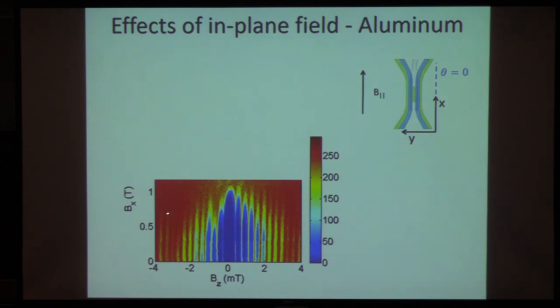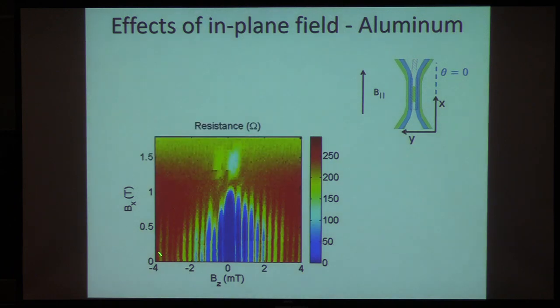And first we thought, oh, this could just be we're killing superconductivity in our leads. This is aluminum, we're applying 1 Tesla. It turns out that we're not killing superconductivity in the leads, and if you increase the magnetic field further, the pattern wants to revive. And you'll see a little bit nicer data in just a minute, but the point is that there's something going on in this system where the Fraunhofer pattern entirely disappears and then reappears again. And we were really puzzled by this for a long time, scratching our heads.